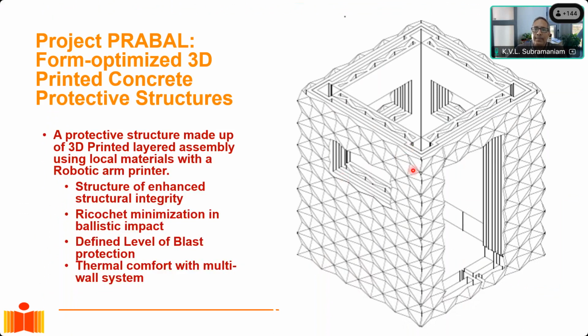And the dimples that you see on the surface are for 2 reasons. One is that it gives a very high level of blast and ballistic protection. And you see the multi-wall construction that we've done here. And if you see the pockets at the end here, these square pockets are where we were able to put in our regular reinforcement and fill it with concrete to give it the structural form.